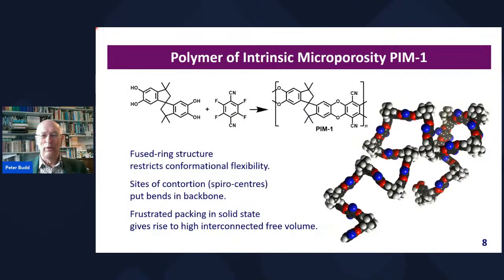And we then went on to apply the same chemistry to create a non-network, a linear polymer. When we originally did this, and this is the polymer that later became known as PIM1, and we also looked at a variety of others, we were thinking of it just as a control experiment because we were focused on network polymers. And in fact, this sat in a drawer for a while before anyone got round to measuring its properties. But then when they did the BET analysis, we realized that we actually had something quite interesting.